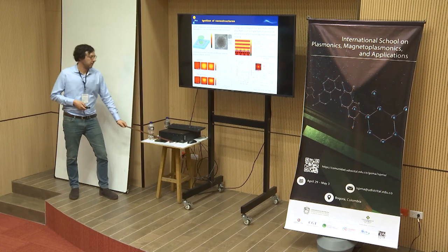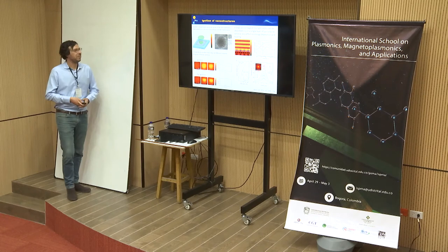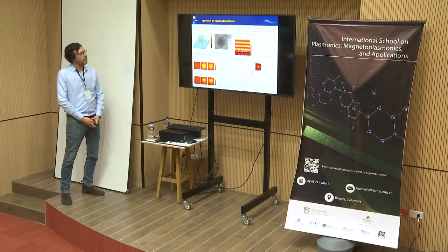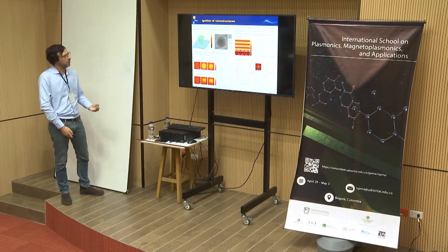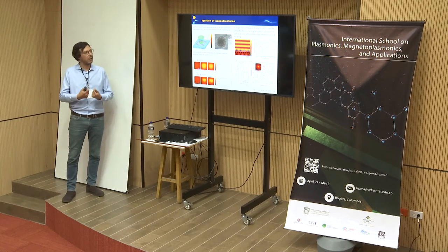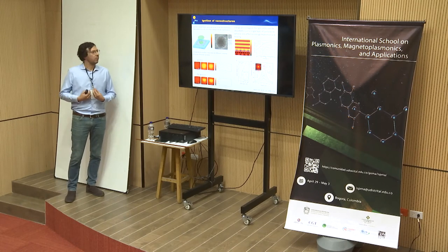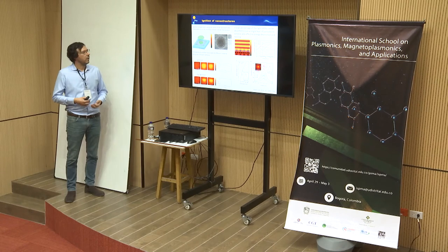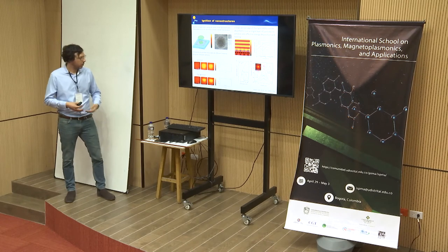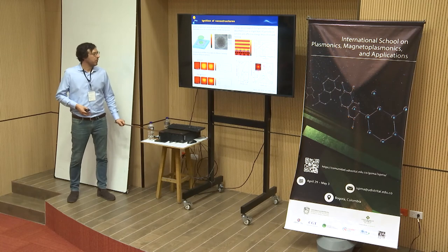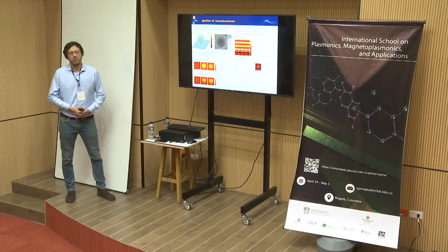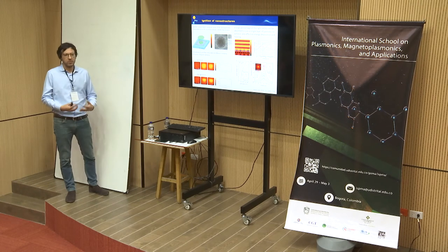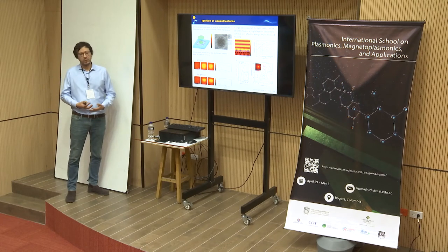And I think this is the last example, so it was very rapid, of this lecture. Another characteristic which I found very interesting of a thermoplasmonic nanostructure is the possibility to have a very high gradient of temperature and heat up your nanostructures very much instantaneously. In this particular example, there was a reported fabrication of aluminium nanodiscs, sustaining surface plasmon resonances, and they induced the ignition, so it's basically the explosion of this nanostructure by the excitation of surface plasmons.